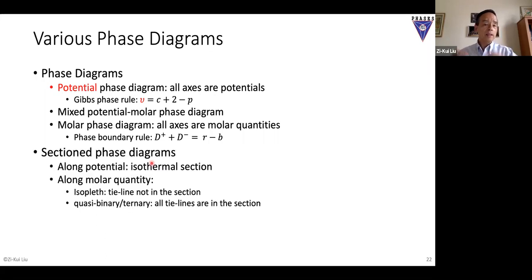Now the multi-component diagram has too many axes, right? You cannot see them. So you cut it, you section it. You can section along the potential. For example, the isothermal section you have learned before. That's a section through temperature. Isobaric is a section through the pressure. Or you can section along a molar quantity. Then you get isopleths. That's important. Tie lines are not in the plane of the section because you cut the tie lines off. That means you cannot get phase fractions using the isopleths. But sometimes you can cut so nicely that you can still look at it as a binary phase diagram. We call it a quasi-binary or quasi-ternary phase diagram.